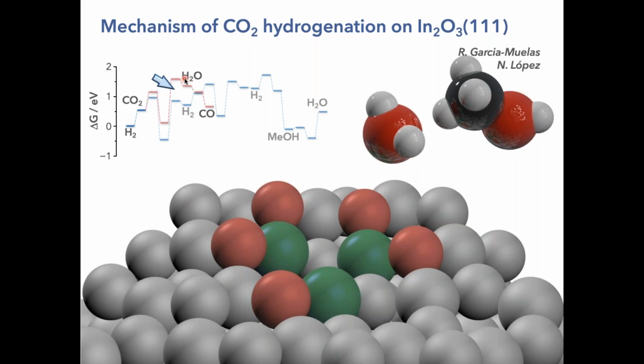So how can we improve the activity of this system, keeping the unique selectivity pattern that we have towards methanol? So to that, we looked into doping effects. So contrary to professional sports, doping in catalysis is absolutely legal and allowed. So we doped indium oxide with a hydrogen splitting element. And obviously one of these could very well be palladium. So no surprise, palladium would be a good hydrogen splitter. And so our first effort was, okay, if we put palladium on top of indium oxide, then we're going to have a good activity because we're splitting hydrogen, but hopefully the selectivity pattern is still determined by indium oxide.